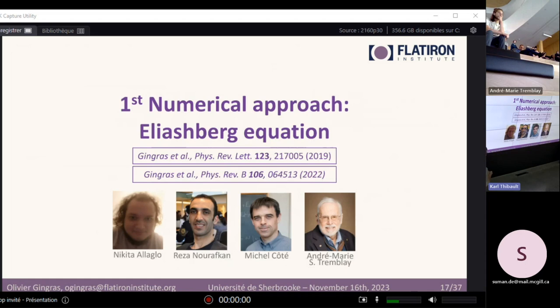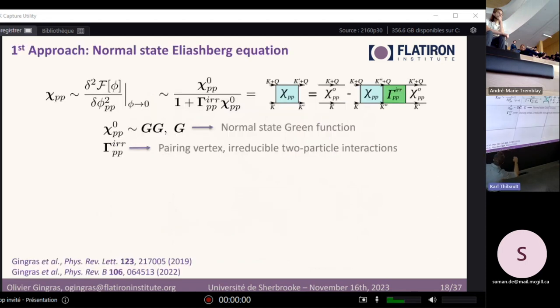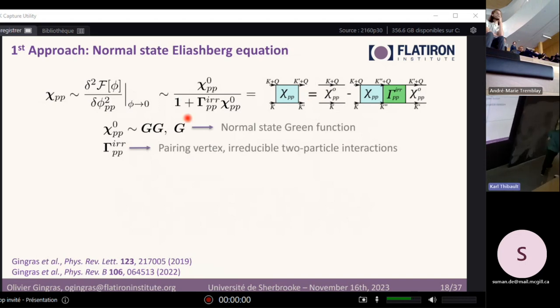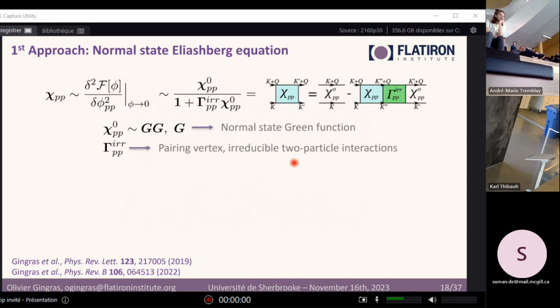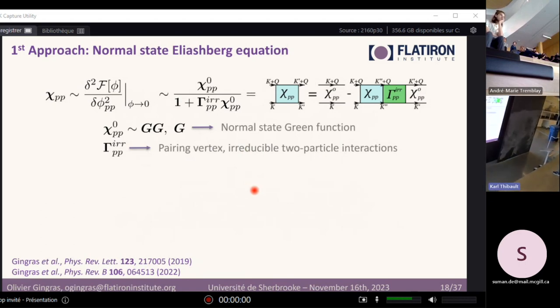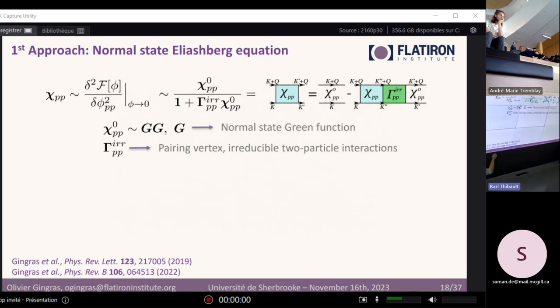So the first work is based on the Eliashberg equation. It's work I've been doing in my PhD with André-Marie, Reza, Nikita, and with Michel Côté from the University of Montreal. Again, the idea here is to compute this pairing susceptibility, which can be expressed as a sum of diagrams. Basically, what it describes is that I have two electrons, two quasiparticles, that can propagate freely, and then I add all the diagrams of how they can possibly interact together through this pairing vertex, which describes all the irreducible two-particle interactions. You can sum all of these orders of diagrams, zeroth order, first order, second, third, infinite, and it gives you this equation here. What you can see is that the propagation of just two electrons will not lead to pairing. It's really the interactions here. So when you consider a glue, then you can have pairing.